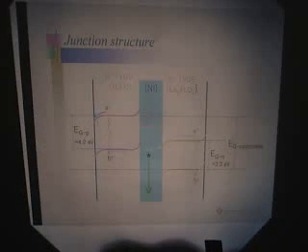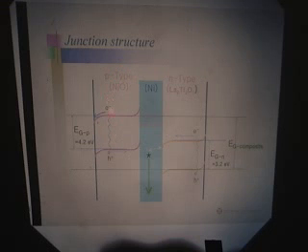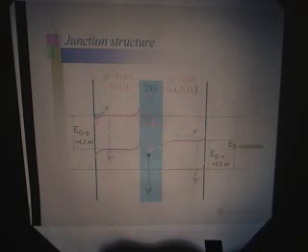And why does this happen? Another conjecture. Okay, this is the model proposed by, I think, among others, Domen a few years back on the role of the nickel oxide on this type of material. One theory is that the nickel oxide is also a semiconductor, so it forms a junction structure. So you have the N-type perovskite material and P-type nickel oxide, and you have the nickel in between as an ohmic junction. And then, the electron generated on this perovskite and the hole generated on this nickel oxide collapse